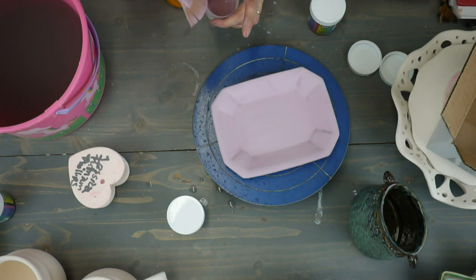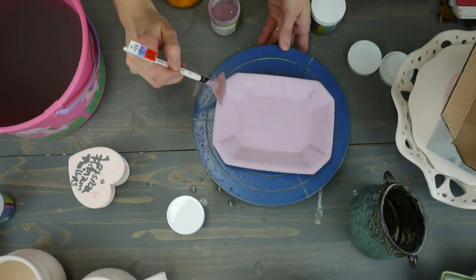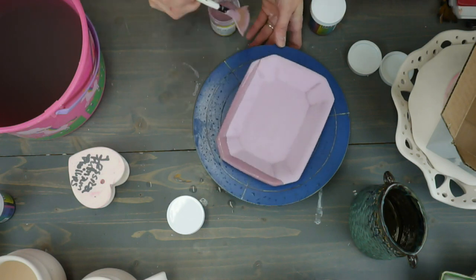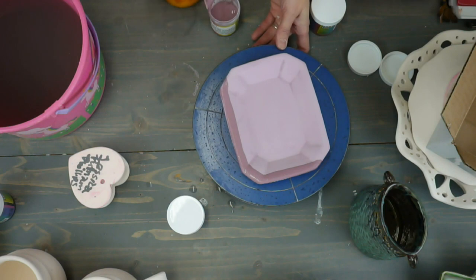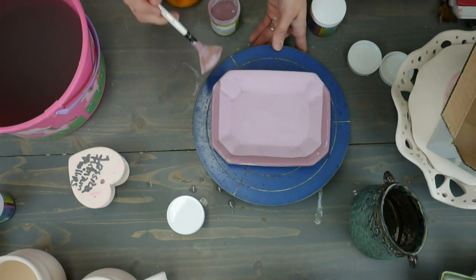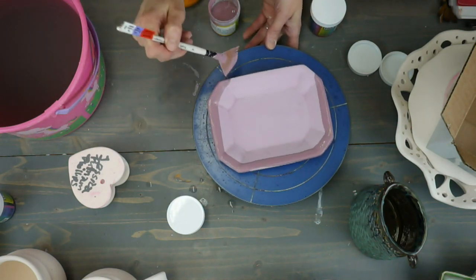So how do you make a brushing glaze usable when it paints on chalky and dries as you're painting? You could try adding some gum solution to it to help it flow better. CMC gum. Pick up some of that and just add the tiniest bit to your container and see if that helps, because that's often used to help a glaze flow to make it more paintable.